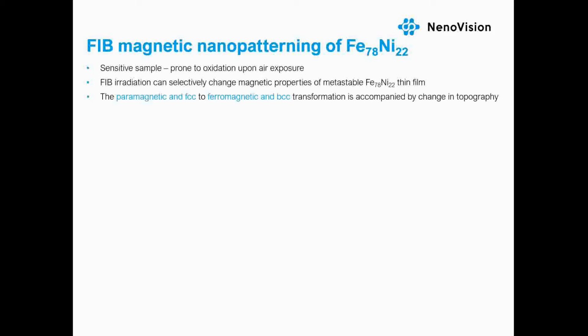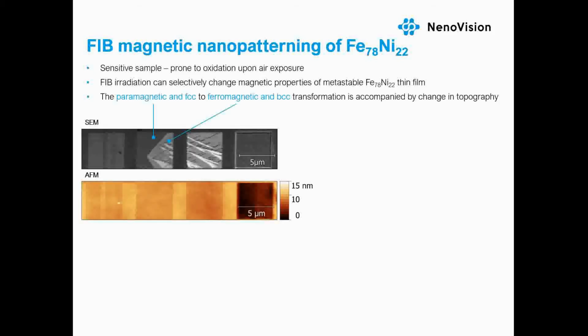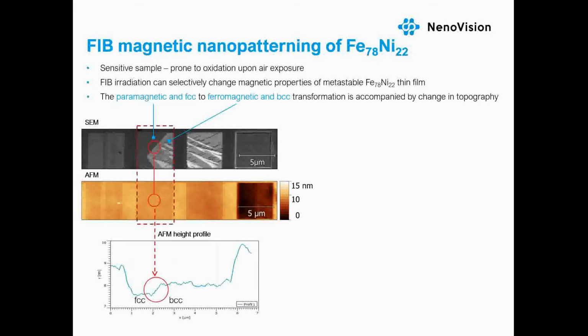Multiple spots in the alloy were focused ion beam milled using increasing doses of ions, as depicted in the AFM and SEM images. The phase transformation is nicely visible in the highlighted squares. Using LiteScope and CPEM technology, it was found that the material transformation is accompanied by topography changes in the range of a few hundred picometers.